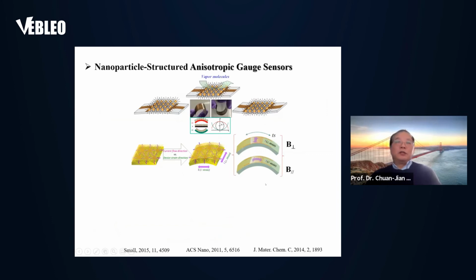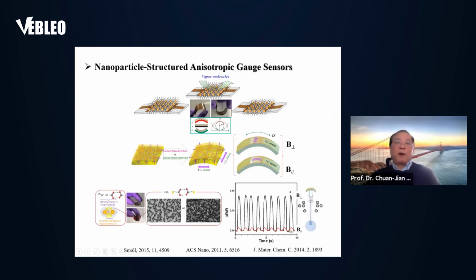Then I also want to illustrate that we can use nanoparticles on this kind of fibrous or flexible sensor to make a strain gauge sensor. You can bend the sensor in different directions, as illustrated at the top. There you can have a response, and this is all a nanoparticle structure. Depending on the bending direction, if it's parallel to the electrodes, you see the response is smaller. If it's perpendicular to the electrodes, the response is much greater. That's very intriguing. We call it an anisotropic gauge sensor. So that's very important nanoscale chemistry.